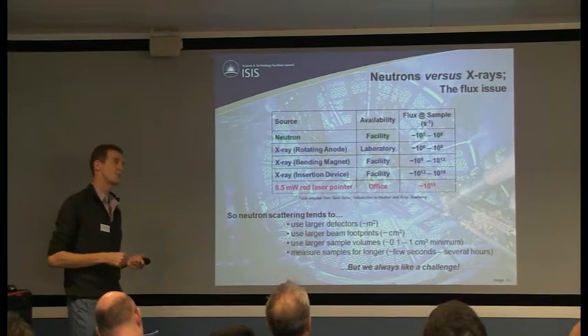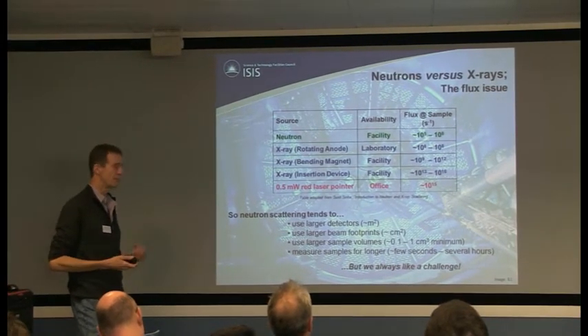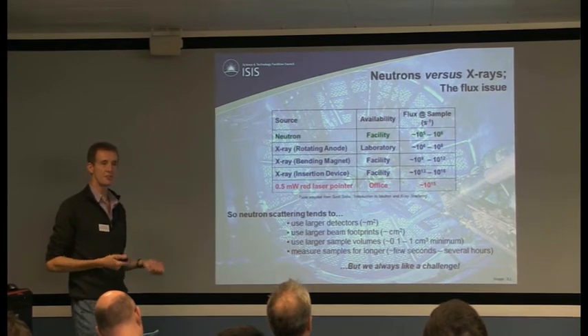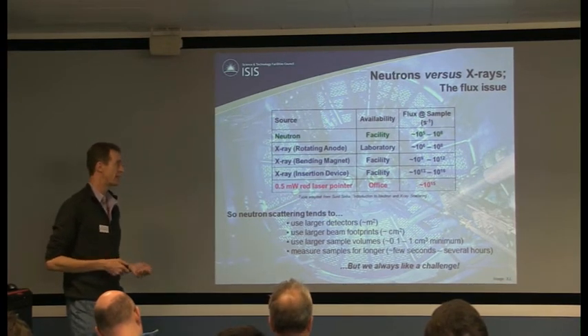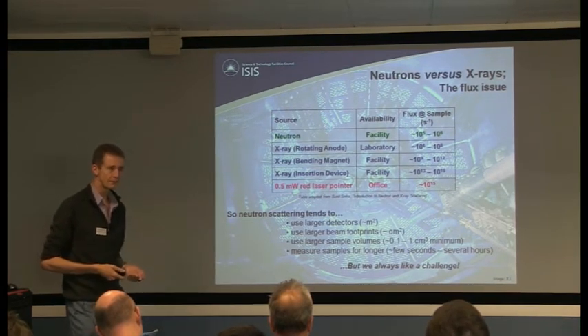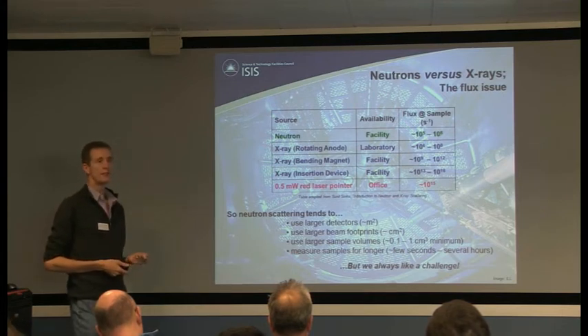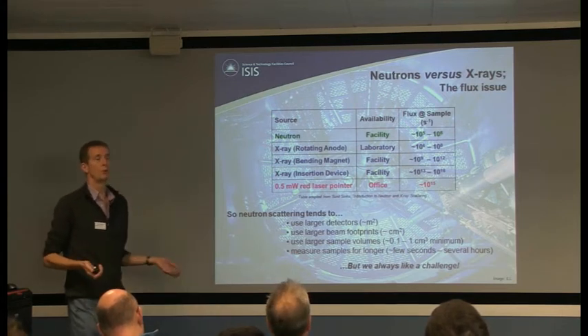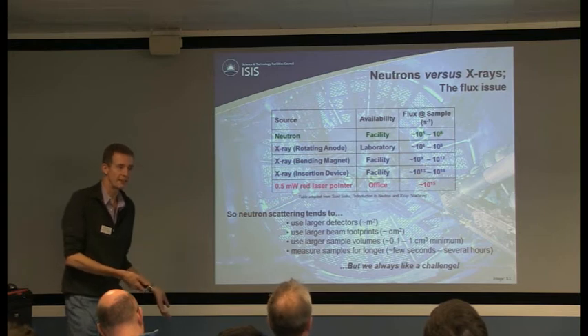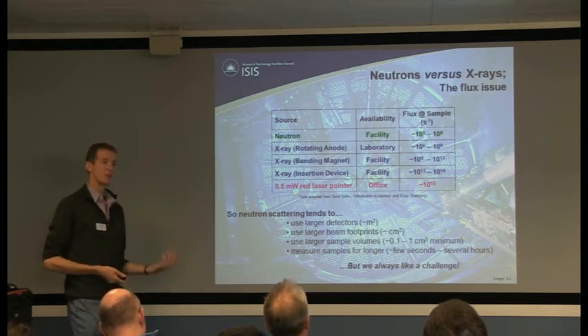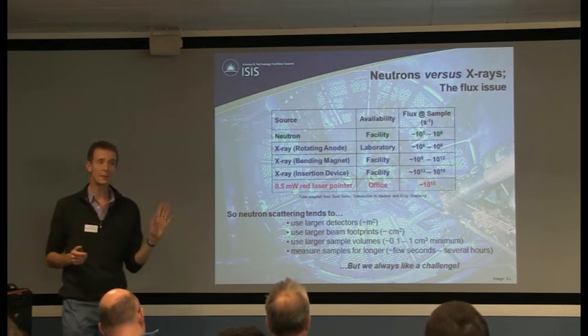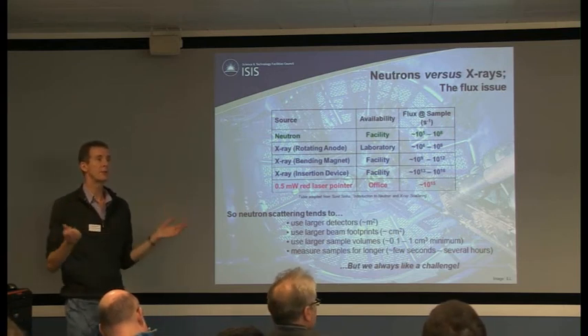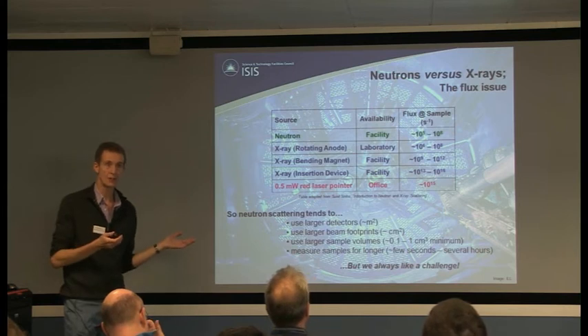Our counting times - we can do experiments on timescales of seconds if it's the right sort of sample, but typically you're looking at minutes to hours. We can't do really, really small samples - well, we could, but then you drop the count rate even further. So our samples tend to be larger than the ones you would use in X-rays. That may not be a bad thing though, it may give you a better bulk average than the X-rays would.